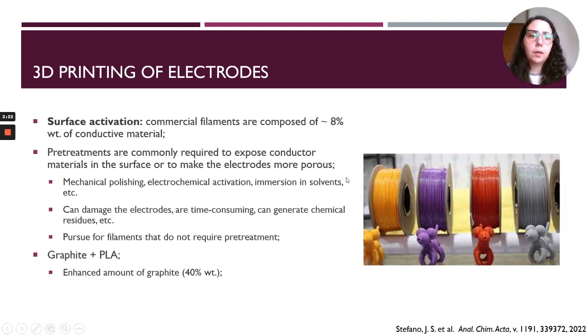Currently, we have a bunch of commercial filaments that can be used to produce electrodes. But the main problem with these filaments is that usually you do require pre-treatments to use them. So some filaments do not have a lot of conductive material in them, almost around 8% in weight is made out of conductive material, and then you need these pre-treatments in order to expose the conductor, to have more conductor on the surface,